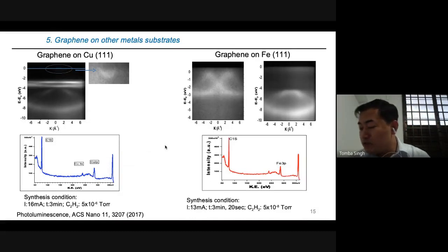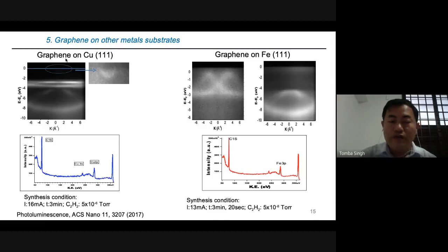As time permits, I want to mention some other graphene synthesis on other metal substrates. We synthesize graphene on copper 111 and iron 111 and others also. According to the different physical properties of the graphene, we can use it for different purposes. So graphene on copper 111 is used for photoluminescence study, and graphene on iron is used to produce different spin orientation because of the substrate iron interaction. Here in the band structure we observe multiple Dirac cones. As I mentioned in the previous slides, the graphene domains are oriented in different crystallographic orientations. That's why we observe different Dirac cones here.